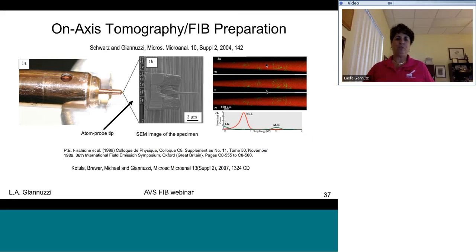The other thing that you can do with these pillar-shaped samples is on-axis tomography. And again, this is work that I did with the group at Sandia. So you can put these pillar-shaped samples at the end on a special holder. This is a Fischione holder that rotates the sample around on axis 360 degrees. You know, you have to do 180, of course. And this is looking at these nanoparticles in a matrix. And so you can do 3D reconstruction and tomography, in this case using EDS.